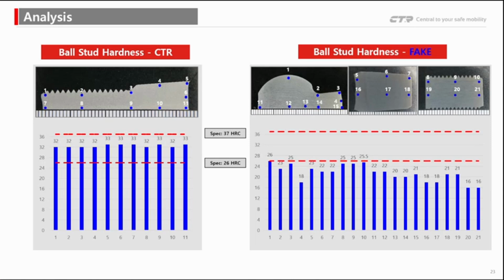variation in hardness. Some readings fall below 20 HRC, which is far below the minimum requirement. These inconsistencies indicate poor, even absent, heat treatment, resulting in much softer material that is vulnerable to wear, deformation, and potential failure. The packed product may look similar on the outside, but when tested properly, its quality and strength fail to meet basic safety standards.